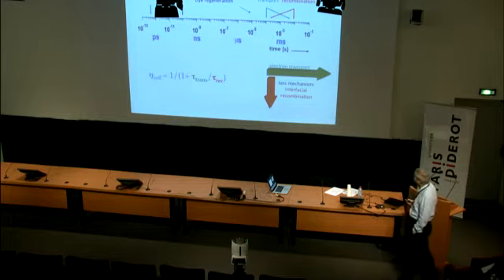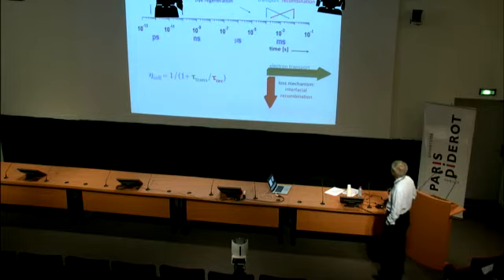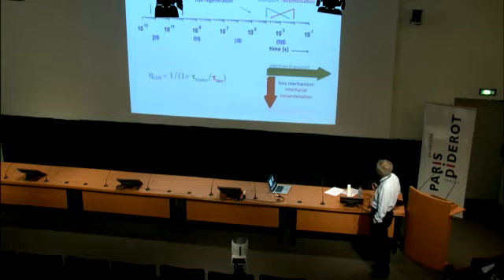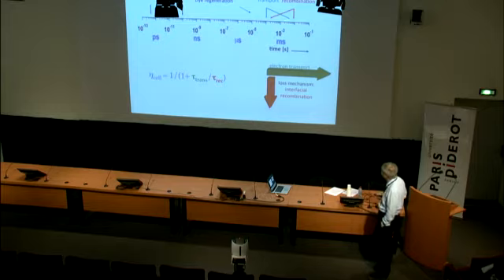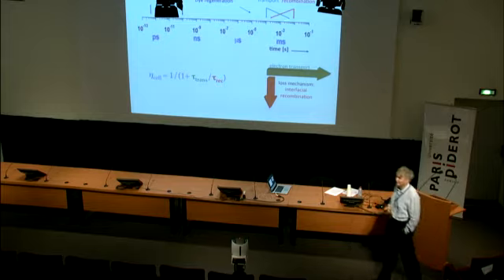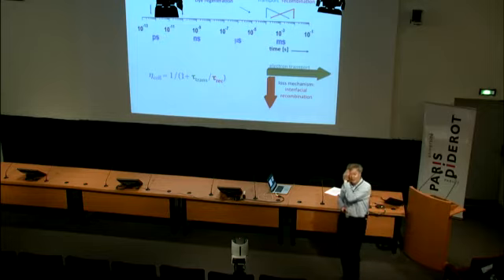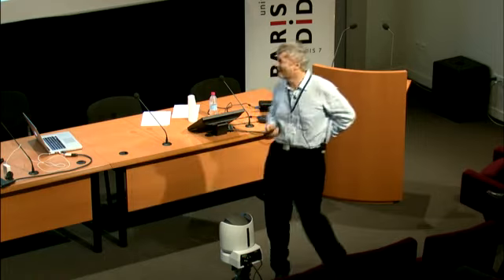And here we have these two time parameters, which are so important. The case I have drawn here is the favorable one, where the transport is 100 times faster than recombination. If this is the case, the collection efficiency is over 99%. This was one of the points where we had discussion, and still a lot of discussion and debate going on. How come that we can collect the carriers from this disordered particle network without having electric field assistance? So it's by diffusion only.